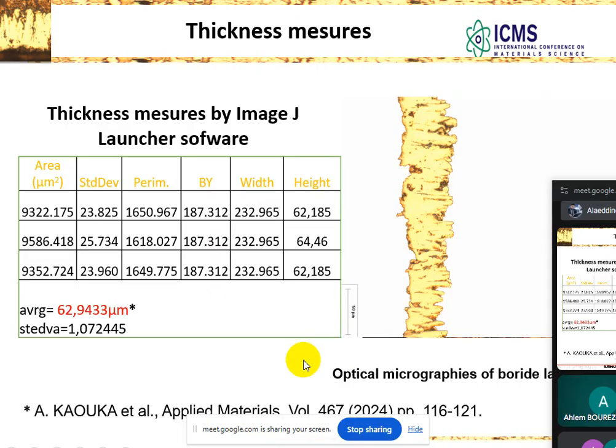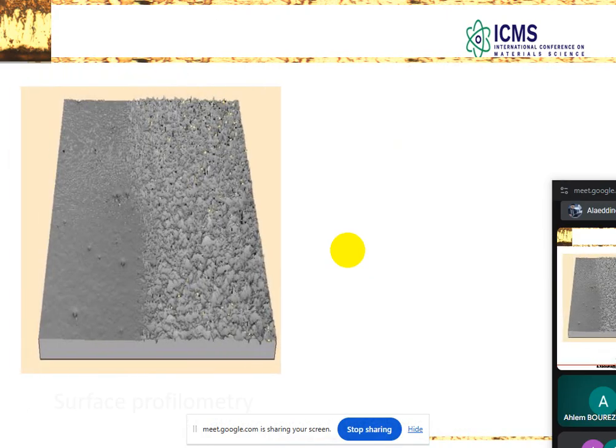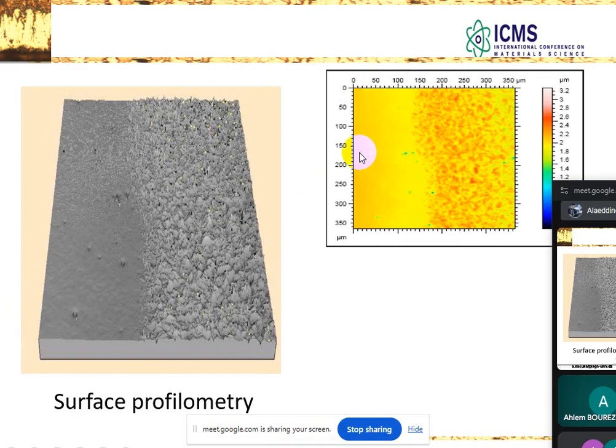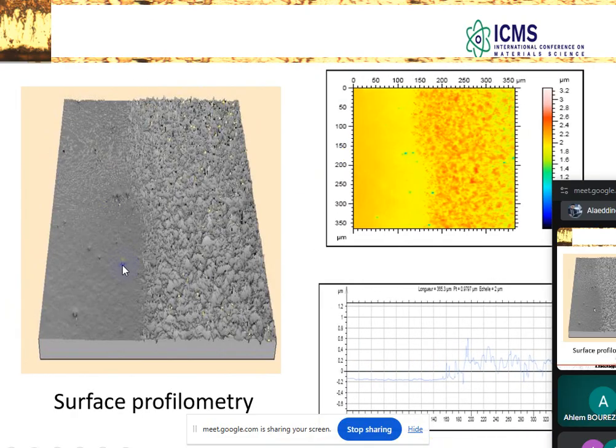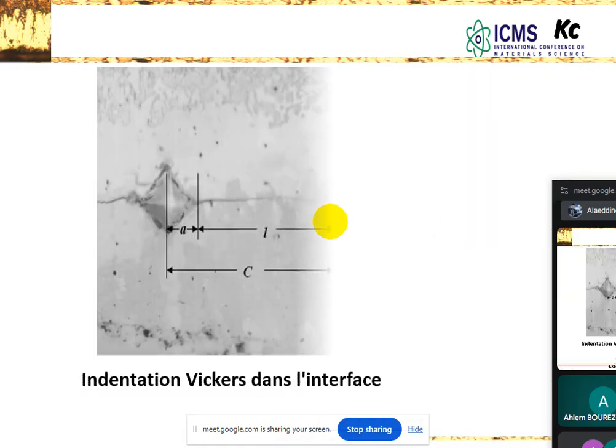So we found that the average is about 60 micrometers, and this is an old result that we have published before, and about 60 up to 280 micrometers, and it's a very important thickness. After that, we have the surface profilometry. On the left side, we didn't achieve the treatment. However, on the right side, we achieved the thermochemical surface treatment, and we have this profilometry of the surface to find the length of the boride layers.